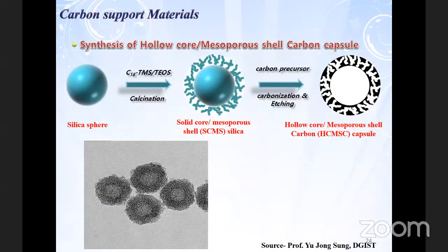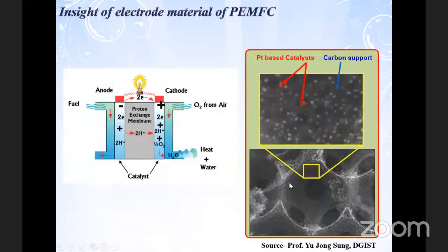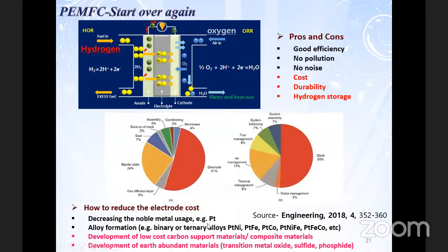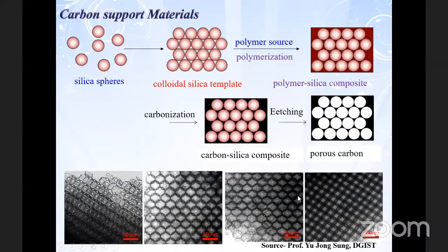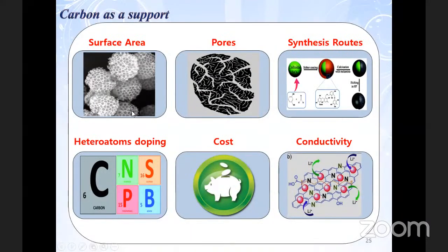There is another method here, the synthesis of hollow core mesoporous carbon. From this group, they prepare the silica, use different polymers and calcine, then again remove the silica material, and they get various carbon materials that can be used as a support. Okay, so with platinum and support, there are these two different areas to work on. Carbon can also be used for the support. Okay, and that carbon material should have very high surface area, enough pores. The synthesis route should be low cost, simple, environment friendly, and cost effective.